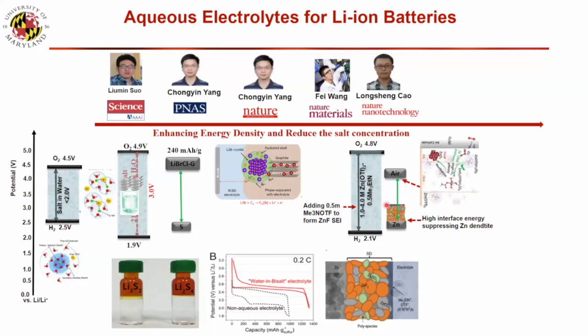uniquely, OTF is hydrophobic. When you increase the cathode potential and OTF absorbs on the surface, it blocks the water. Then we find that if water is not involved in the cathode oxygen reaction, it really has a two-electron reaction that is really fast. So this is one way we use the knowledge from aqueous batteries to develop a zinc-air battery.